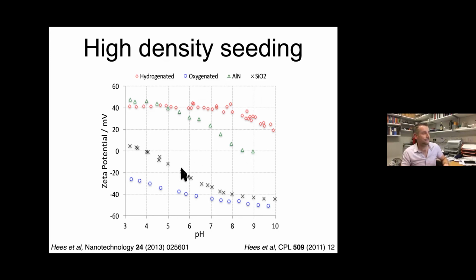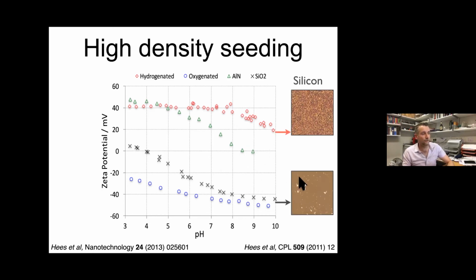So if you look here, where we just characterized silicon dioxide, these particles are never going to stick to each other. They're repelling from each other. So if you try and do an AFM afterwards, what you see is this really awful nucleation here. So what you need to do is reverse the zeta potential. And the easiest way to do that is just to heat in hydrogen. And then you get enormously high densities.